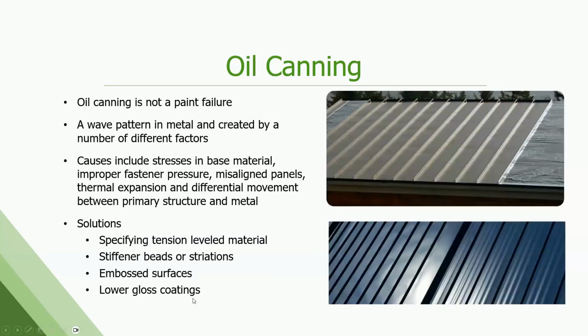Oil canning, buckling. You can see the buckles on here. It's a great example at the bottom how to get out of it. So a long span, 20 plus long panels, this is going to be more predominant. If you put a striation or a pencil rib in the forming, it takes that away. Lower gloss material hides this too. It's still there, but because you don't have that shine off the surface, it's really hard to see it. So matte finishes tend to hide this. This is just an inherent nature of light gauge steel being used for roofing panel.